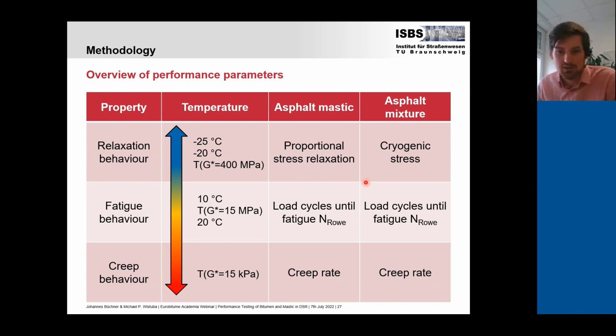So I did not go into detail on how to determine these values for the mixture, but they can be determined from these performance tests mentioned before. The creep rate is a quasi-static constant creep of the material. The load cycles are determined with the energy ratio, and the cryogenic stress is just determined from the curve of the cryogenic stress at the specific temperatures which we used here.